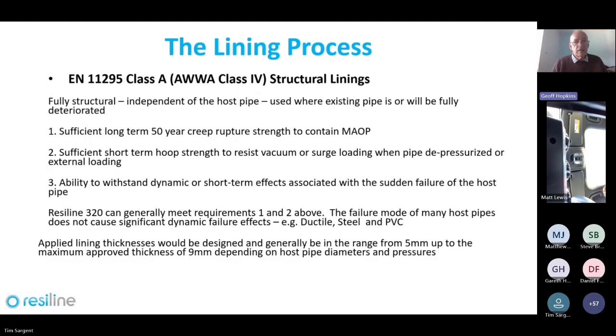Next slide, please, Tim. Fully structural linings. There are 3 requirements. It has to have sufficient long-term creep rupture strength to contain the maximum allowable operating pressure and be capable of short-term hoop strength to resist vacuum or surge loading. We can generally meet those first 2 conditions. The failure mode of many host pipes doesn't cause significant dynamic or energy release effects. So for ductile iron, steel and PVC pipelines, yes, we can put fully structural linings in.